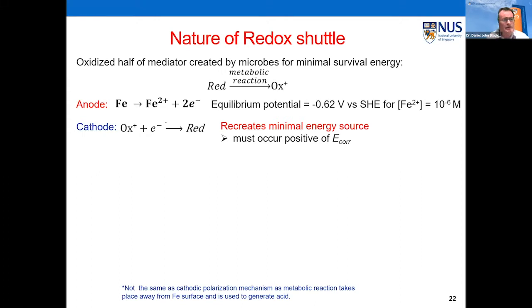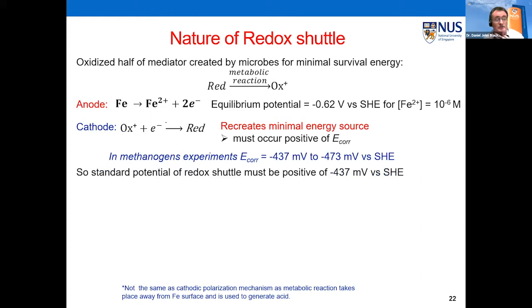What do we know about the cathodic reaction? Well, this oxidized species, which is produced in the metabolic reaction, has got to be reduced again as the cathodic reaction that causes the corrosion. That recreates the mediator energy source. It's got to be positive of E corr. When we measured E corr in our experiments, they were up to minus 437 millivolts versus SHE. So our standard redox potential must be positive of that. Okay? Otherwise, open circuit potential cannot be up to that sort of value. The more positive it is, the more energy we'd have to drive the corrosion.